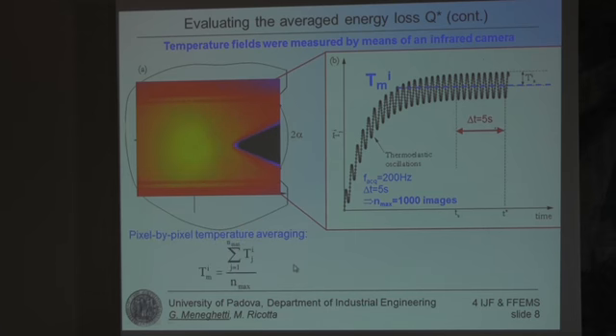Now, if we perform a pixel by pixel temperature averaging, we can calculate quite easily this mean temperature signal, and this can be done by commercial software sold with the infrared camera, and then after that we can evaluate the gradient of the thermal field to evaluate the mean energy loss. So this quantity is the one appearing in this formula.